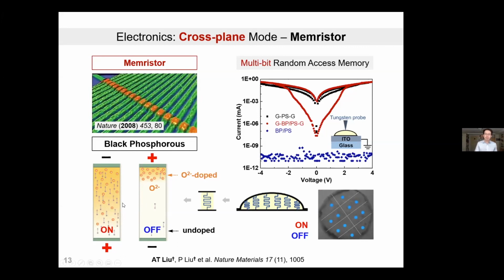The top and the bottom electrode of your memristor are graphene, correct? Yes. We used ITO as the bottom electrode, and graphene sits on top, and the tungsten probe just directly comes down and contacts the graphene on top. And you're counting on a high series resistance, lateral resistance of graphene, so that you only write a small spot under your probe. Exactly.